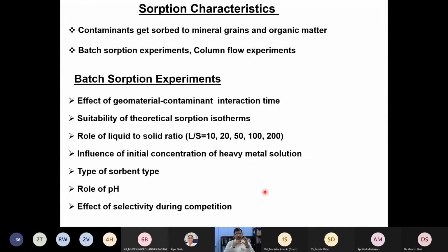One is batch sorption experiments or column flow-through experiments. In case of a batch sorption experiment, it's very, very simple. What you do is you take a bottle and you put some amount of the material of your interest, the sorbent, either soil or the geomembrane or whatever it may be, and you fill it with the contaminant of your interest, and then you keep on shaking for some time, allowing a certain amount of sorbent-contaminant interaction time, and then at the end of the interaction time, the equilibrium time, you take it out and separate the sorbent and the sorbate.